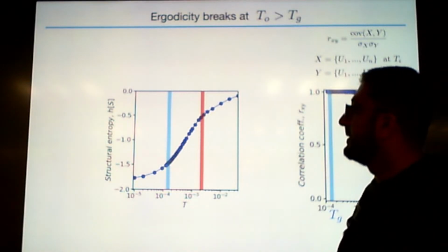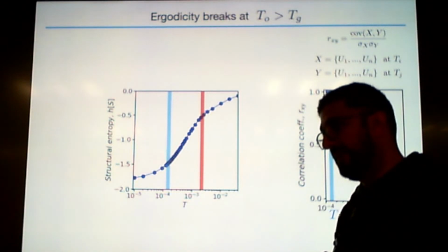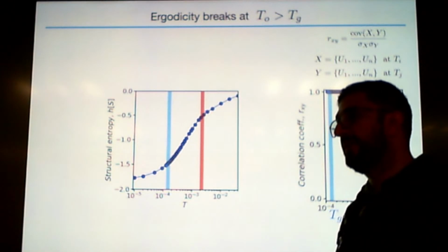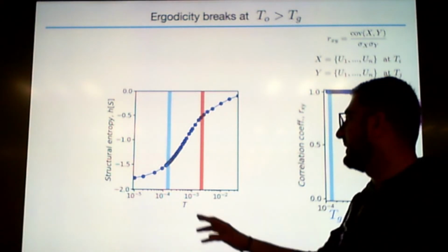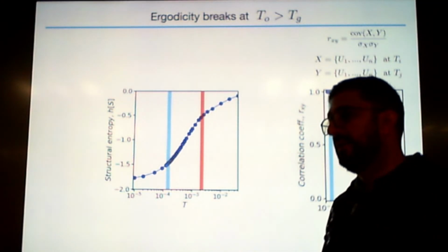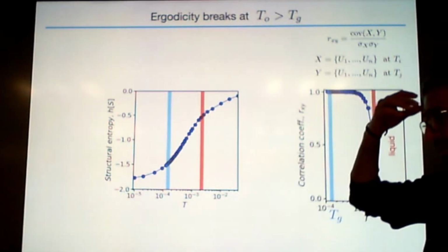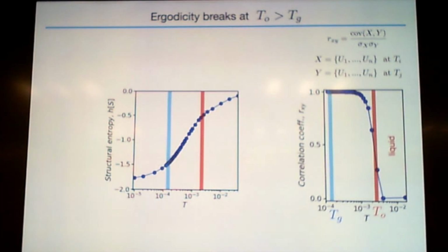It's the S2, what people call S2, structural entropy based on the g(r). But in this case, it's based on the S(k). It's the one I showed in the very beginning. It's a functional of the structure factor, or a functional of the g(r). What that means is basically you're measuring entropy based on your pair correlation functions, without any orientational, I mean just,